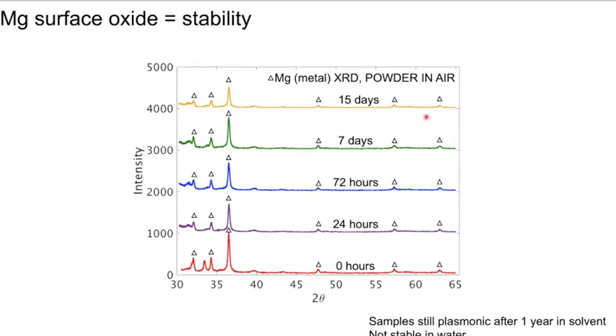And they remain plasmonic even in air, they remain metallic even in air. This is magnesium nanoparticle powder that still shows a signature of magnesium metal by X-ray diffraction after even 2 weeks in air. That was done in Houston, with pretty humid air.